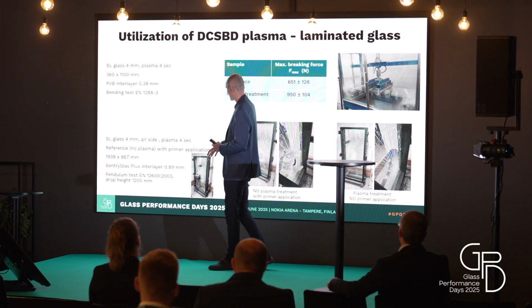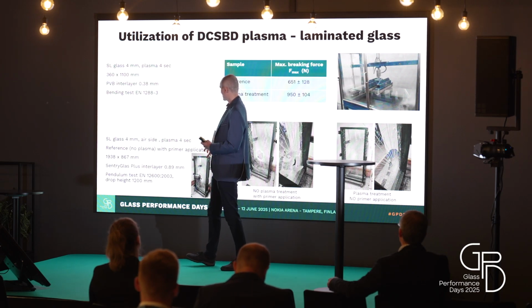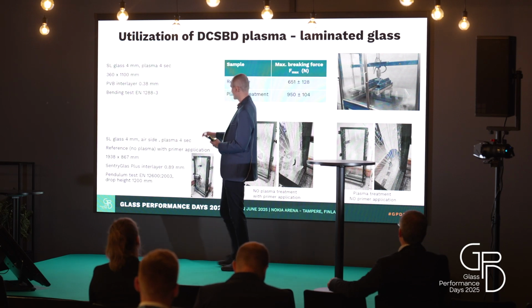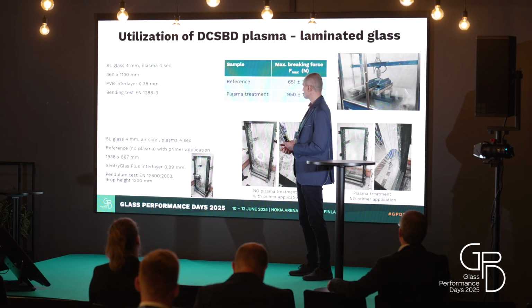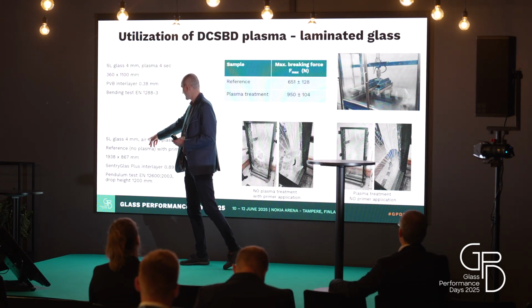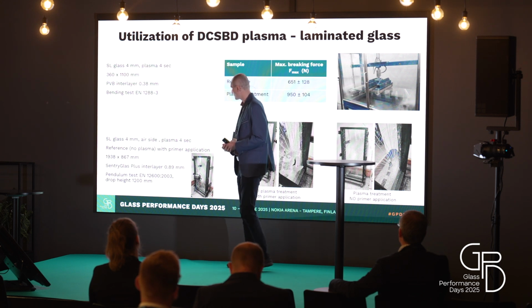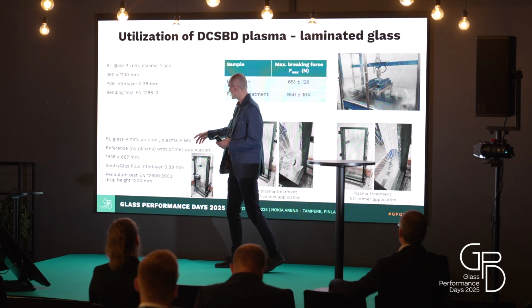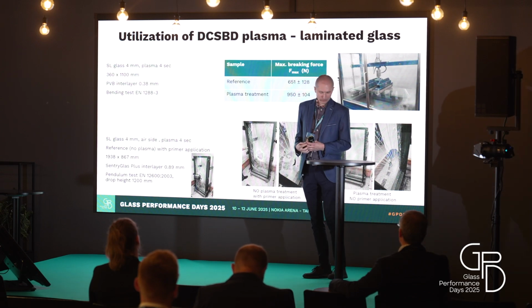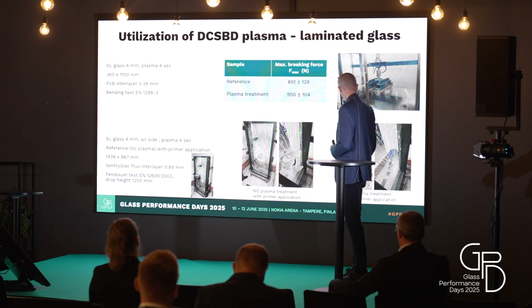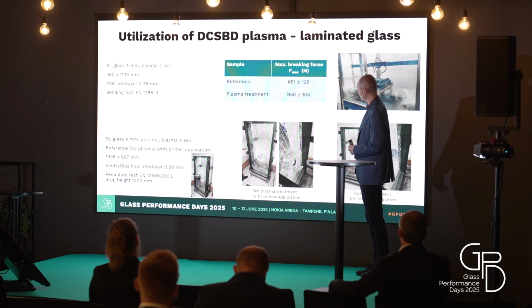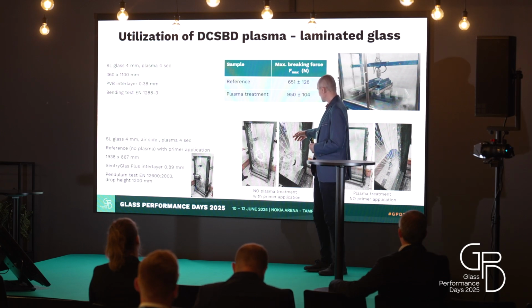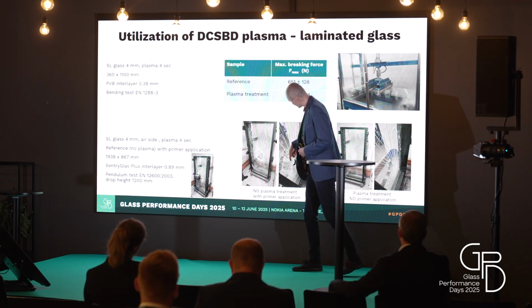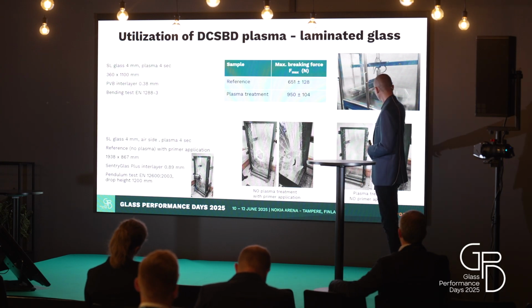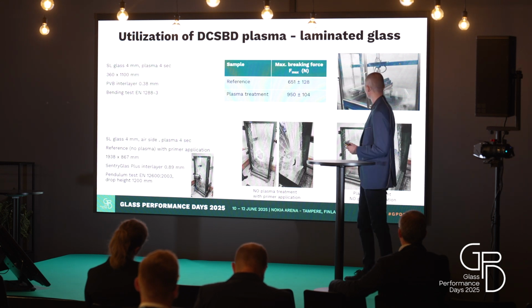This is a pendulum test done on large sheets created with a SentryGlas ionomer interlayer. In this case, we work with the air side, also with a very short treatment time applied. In the case of reference samples, we had to use the primer, of course, but when plasma was applied, we used no primer. And here we have the result after the pendulum test. The samples without any plasma treatment, with just primer application, failed the test, as we can see here in these pictures. And here there are, of course, some cracks, but there is no direct breakage of the sample.